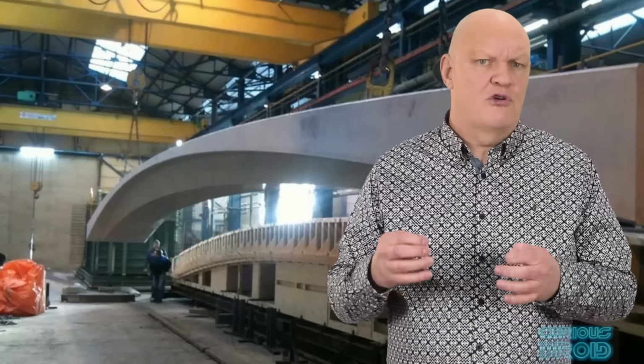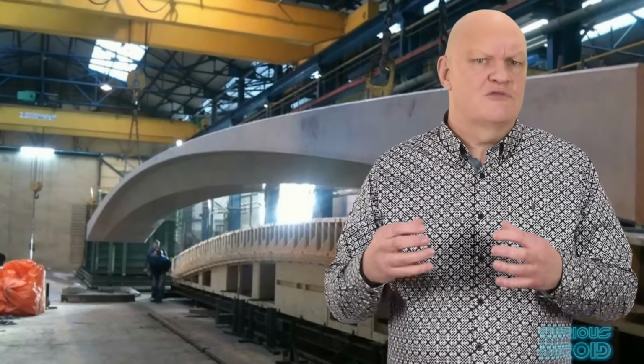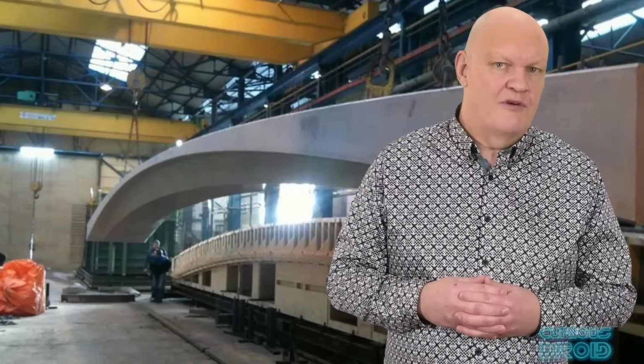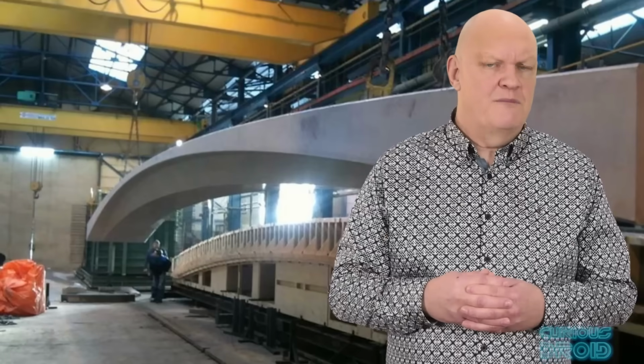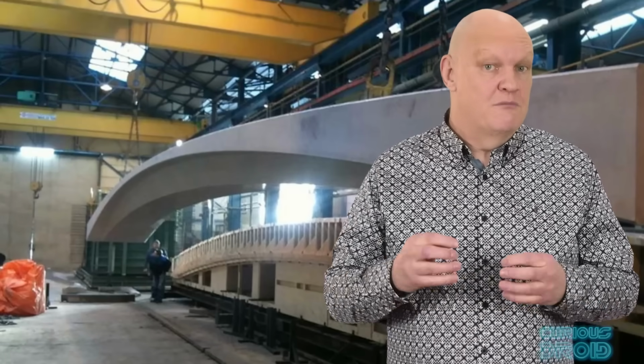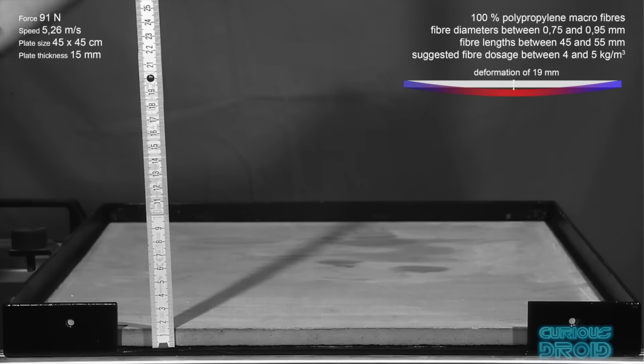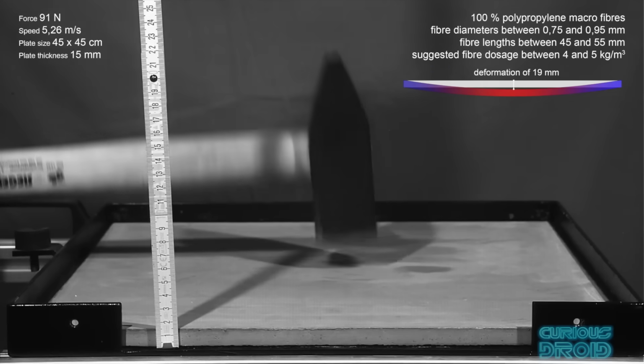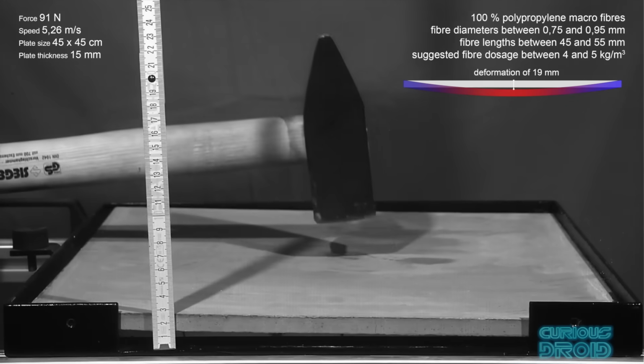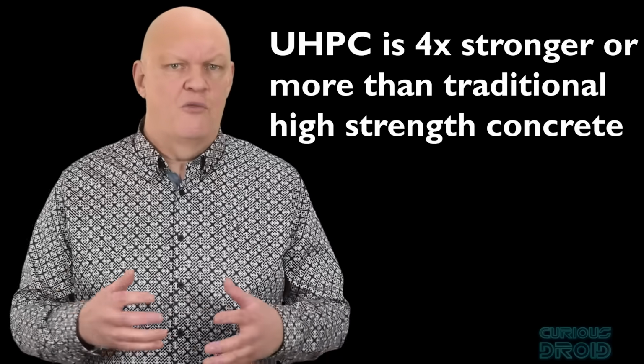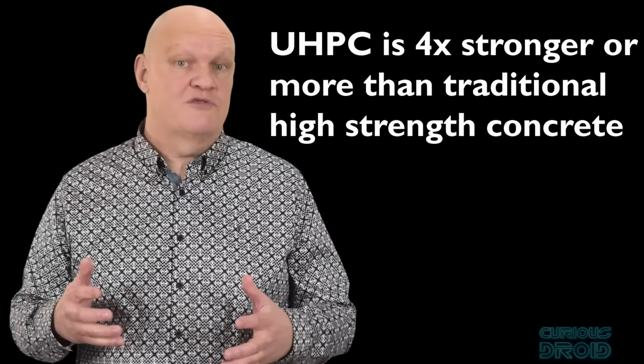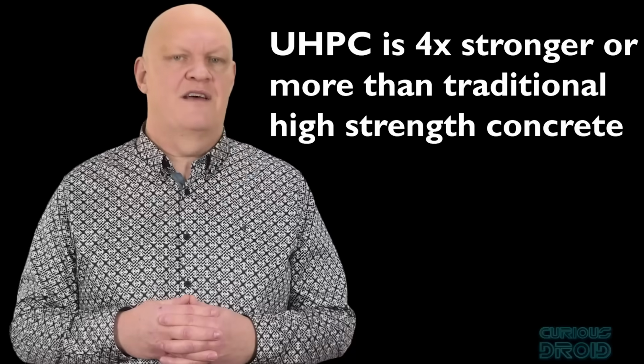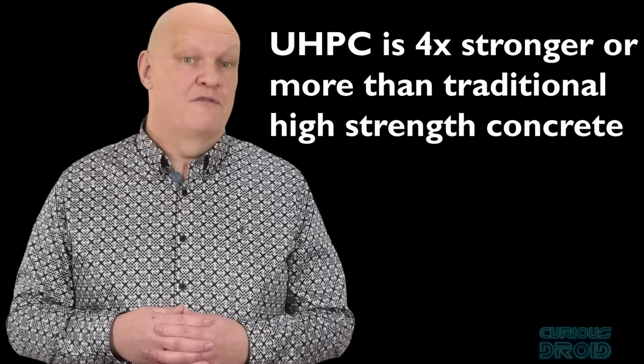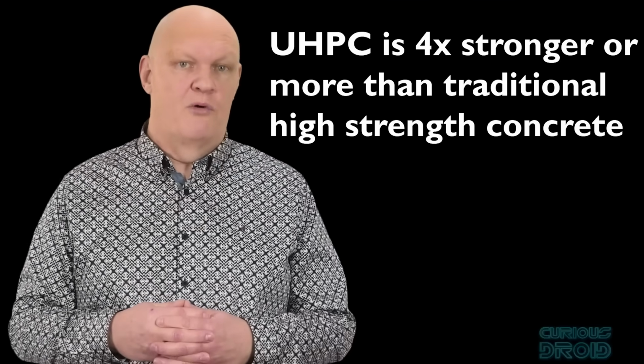The finer, purer quartz and sand produces a smoother, denser concrete that holds together better, and when combined with the fibres, the new UHPC is much less brittle and has far more fracture energy, meaning it takes more energy to split it open. Compared to the normal high-strength concrete, which had a yield strength of 5 to 10,000 psi, UHPC has a yield strength of 40,000 psi or more.